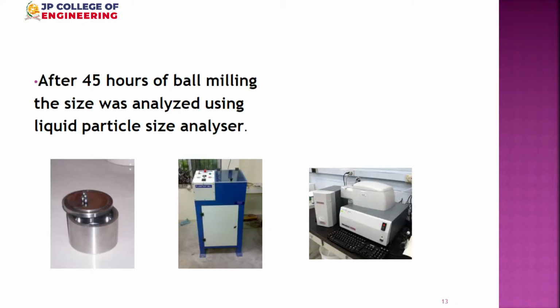Yeah, so this is the ball mill. We took a small stainless steel chamber with thick walls. Inside you put the fly ash particles. The second picture shows the machine in which you put them, and then it is gyrated, rotated at a very high speed. Then the particle size undergoes reduction. The third picture shows a particle size analyzer where you can check the distribution of various particle sizes. Okay, yeah, next slide please.